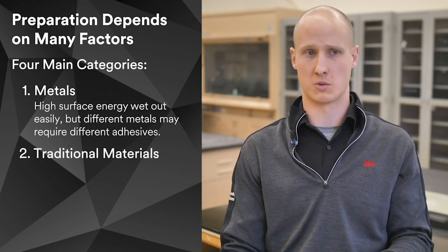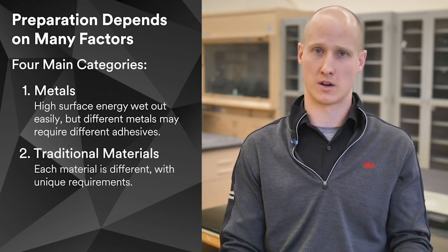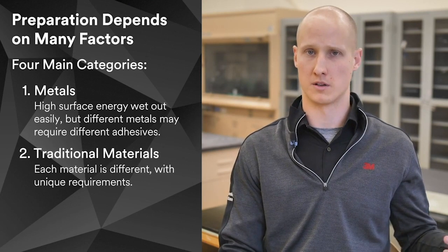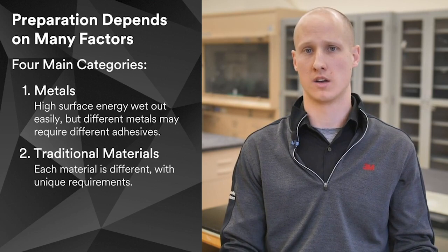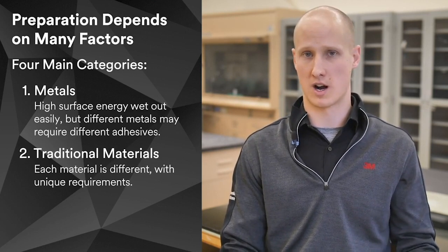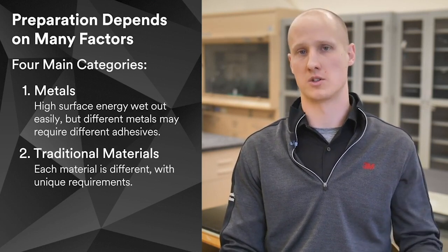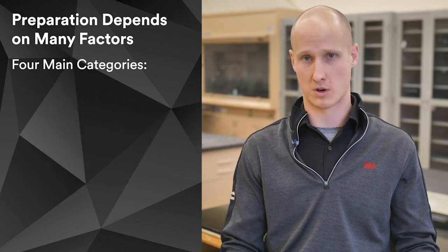Traditional materials, when you have things like natural leather that have oils in them from the tanning process that will leach into the adhesive over time, that could plasticize it and degrade the bond, or like I mentioned, glass with hydrolysis. So moisture penetration is sensitive when you have an adhesive glass bond.